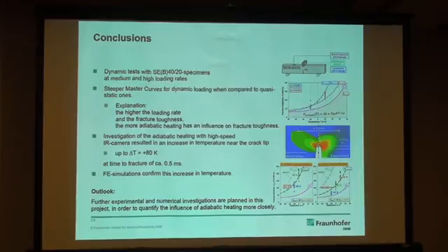What I could tell is that we observed some local crack arrest phenomena along the crack front and in the stretch zone, which increases with temperature. This can be an effect that explains why we've got higher fracture toughness with an increase in temperature. We've investigated the heat generated with an infrared camera and measured a value of an 80 Kelvin increase in temperature, which was also quite nicely predicted by the simulation.